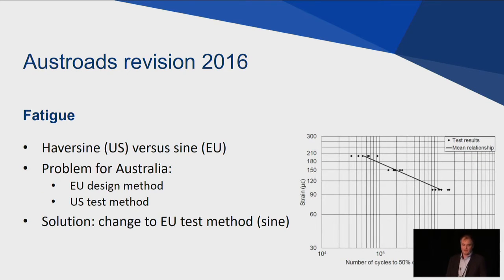Then, in terms of fatigue, we had a problem. You may be familiar with the discussion around Haversine and sinusoidal testing in fatigue testing. That's the fact that Haversine displacement loading results in a sinusoidal strain response in the sample after a number of load repetitions. Now that's not a problem if you've used your Haversine testing to calibrate your fatigue models. Unfortunately, what we had in Australia is we were using a European design method, which was based on sinusoidal testing, in combination with a US test method.